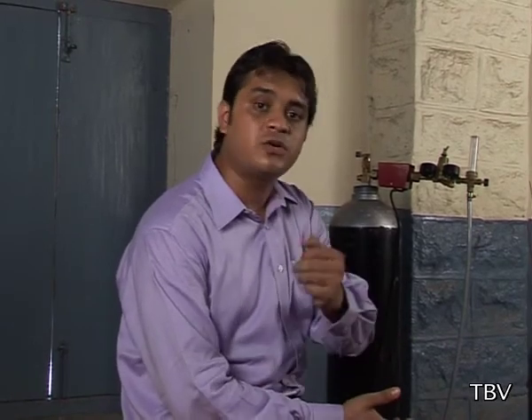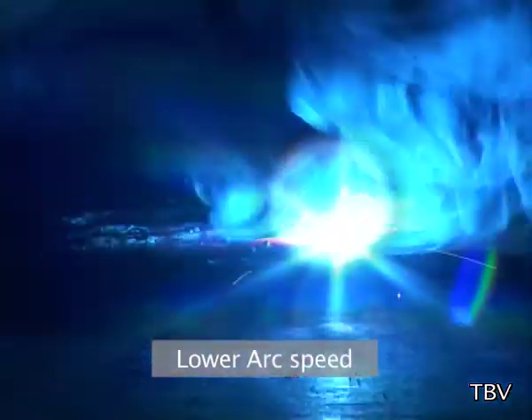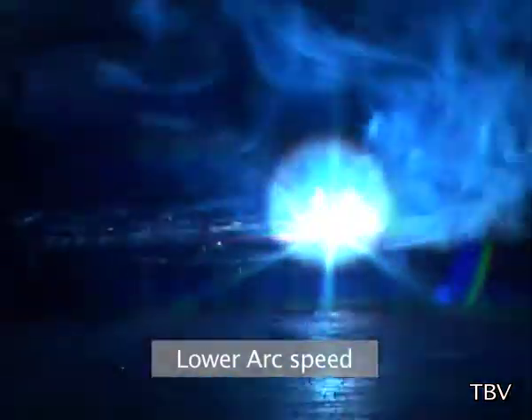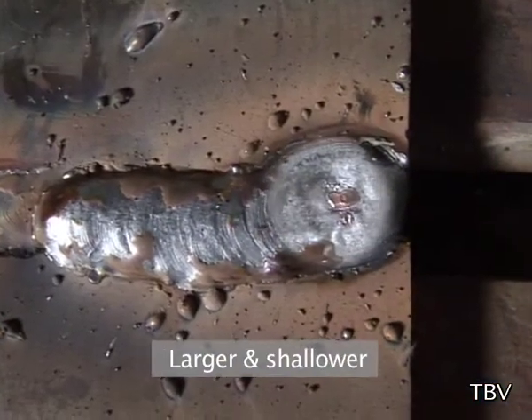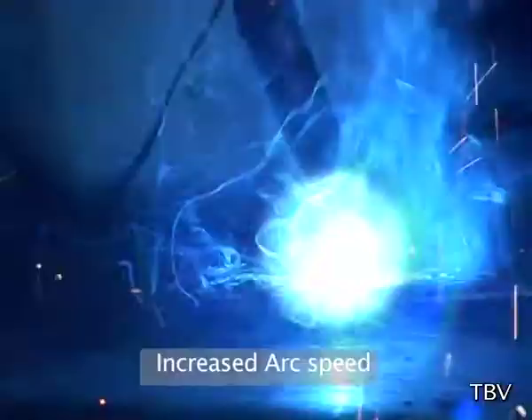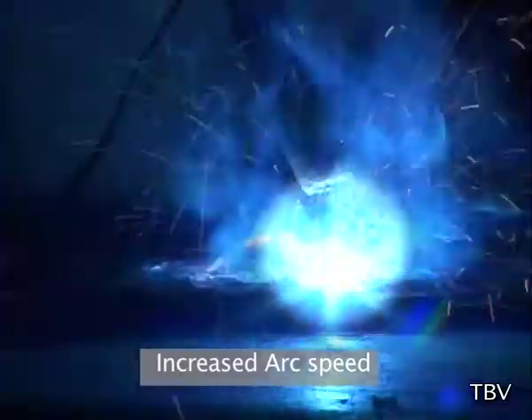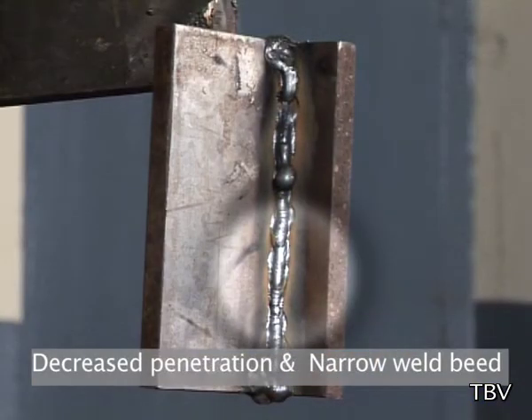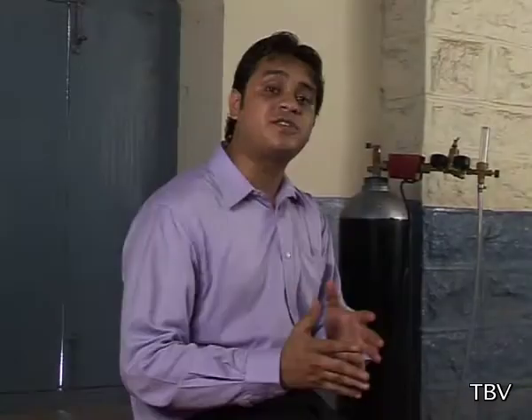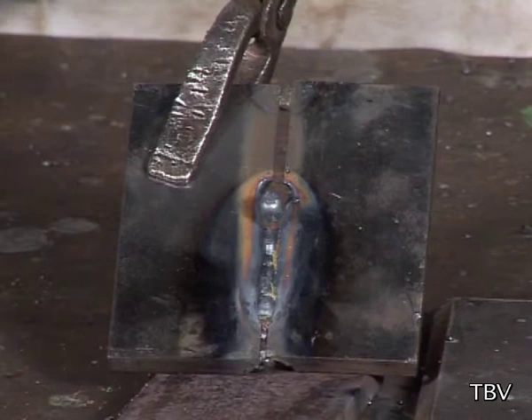Arc travel speed. The linear rate with which the arc moves along the joint, known as arc travel speed, also affects weld bead size and penetration. If the travel speed is lower, the weld pool becomes larger and shallower. As the speed increases, the heat input rate of the arc is decreased. Therefore, there is decreased penetration and a narrower weld bead. If the travel speed is excessive, undercutting occurs along the weld bead because the deposition of the filler metal is not sufficient to fill the parts melted by the arc.